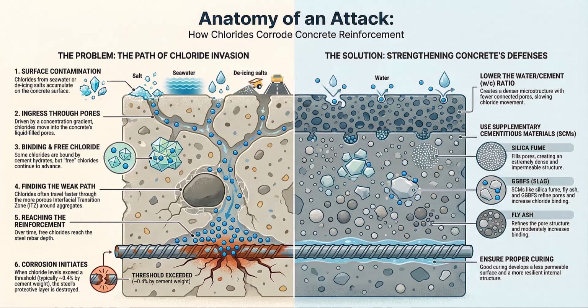That's the baseline. Now let's look at penetration depth after 10 years of exposure. This is the clearest metric. In a standard OPC structure, after only a decade, the chloride front penetrates deep, often 25 to 45 millimeters. And if you only had 50 millimeters of cover over your steel, you are already halfway through your service life and flirting dangerously close to the rebar.